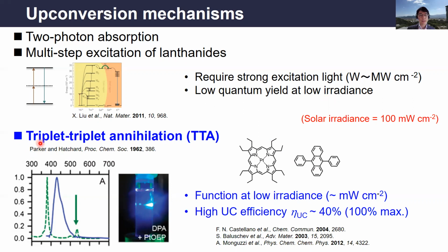So instead, people have recently looked at triplet-triplet annihilation, TTA-based upconversion. It was first demonstrated by Parker and Hatchard in 1962, and it is gaining renewed attention these days because it can be useful for solar applications. The biggest advantage of this molecular system against the other mechanisms is that it works at weak excitation intensity, like sunlight irradiance. And its efficiency can also be high. The most basic, popular combination of donor and acceptor gives 40% efficiency, out of a 100% maximum.